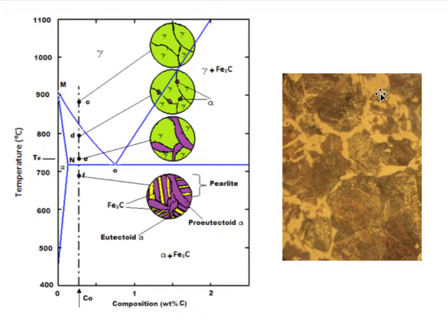Of course, we need to look at a large part of the sample in the microscope, as large a part as possible. And then there are different techniques. One can use image analysis directly from the microscope, which is the best, but one can also use simpler techniques by putting lines and measuring how large a portion of the line is in the respective phase. If we do so in this case, we end up with a result that shows that we have 75% pearlite and 25% ferrite. With that data, we will go into the phase diagram.